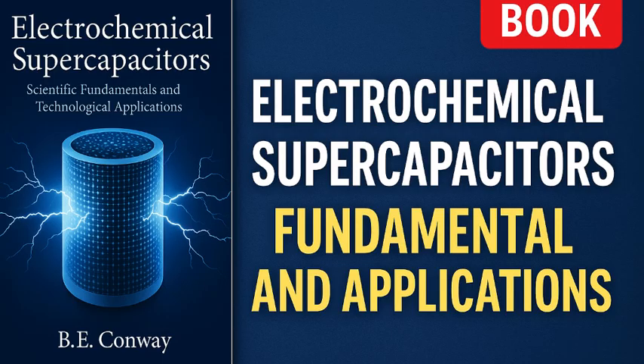Conway describes multiple mechanisms, including activation controlled Faradaic processes and diffusion controlled leakage. For example, if there are trace amounts of redox couple in the electrolyte, it could continuously discharge the capacitor internally by shuttling electrons, or functional groups on carbon might slowly react. Self-discharge is measured by either noting voltage decay over time at open circuit or by leakage current under constant voltage. Engineers mitigate self-discharge by high-purity manufacturing, sometimes adding electrode balancing or voltage management circuits when multiple cells are in series, so one cell that self-discharges faster doesn't drag the others into reverse or overvoltage.